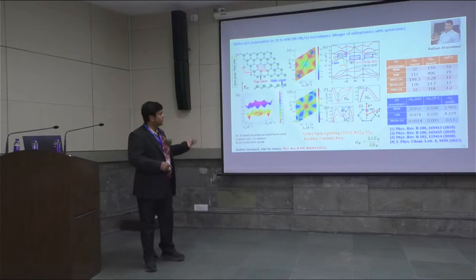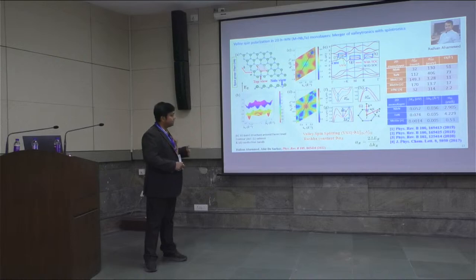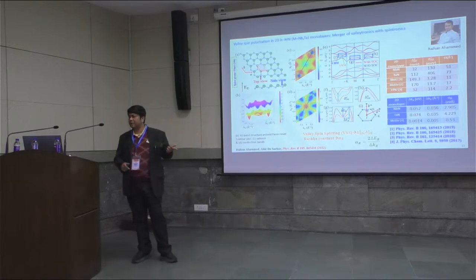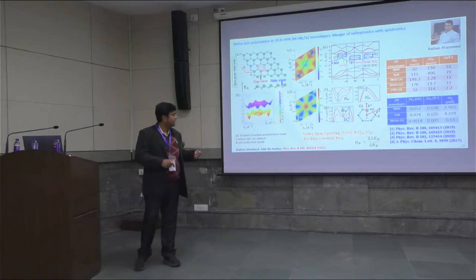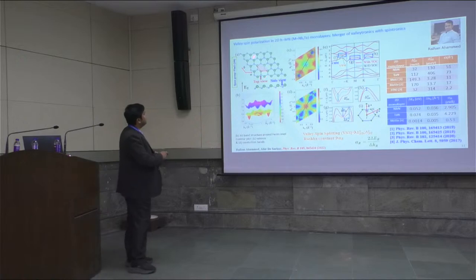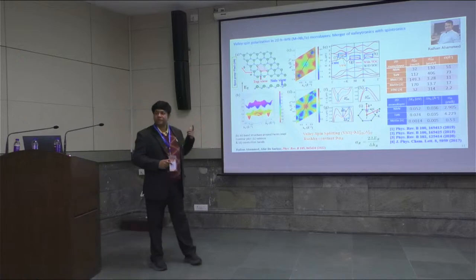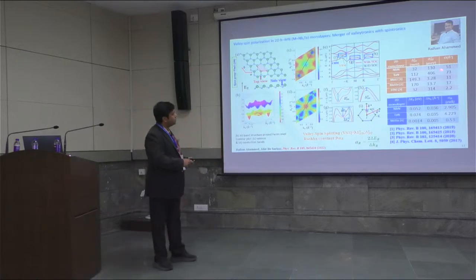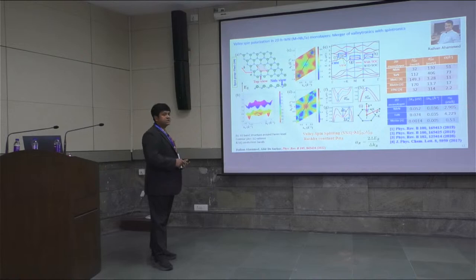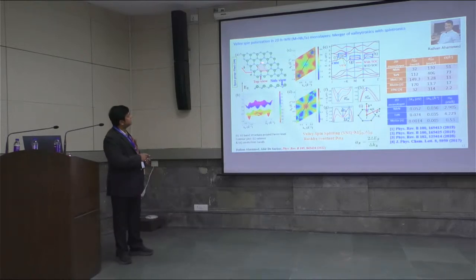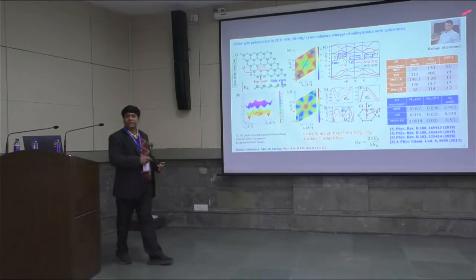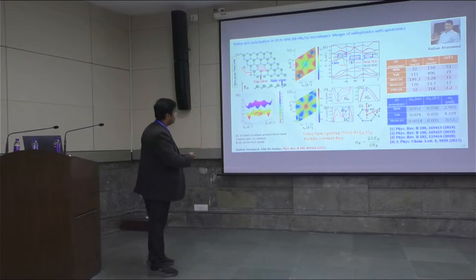The Rashba constant is quantified by this parameter, and the higher the Rashba constant, the better for spintronics applications, where spin degrees of freedom are utilized. And also it has a large spin orbit coupling, and the inversion symmetry is broken, and therefore it shows a high Berry curvature, which is much higher than several two-dimensional materials. So this shows also a reasonably good Rashba constant. And therefore, we propose that these monolayers will be suitable for the integration of valleytronics with spintronics.